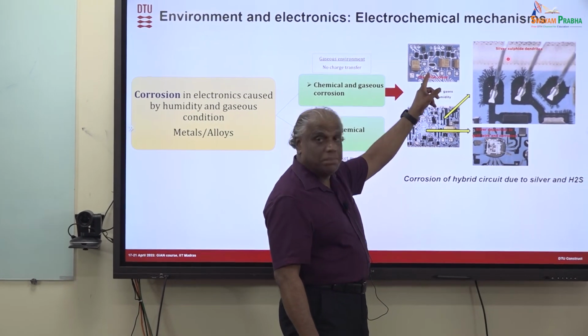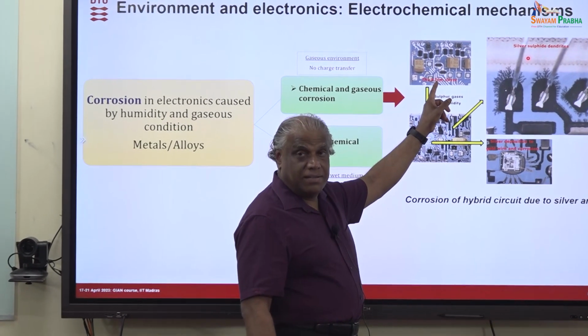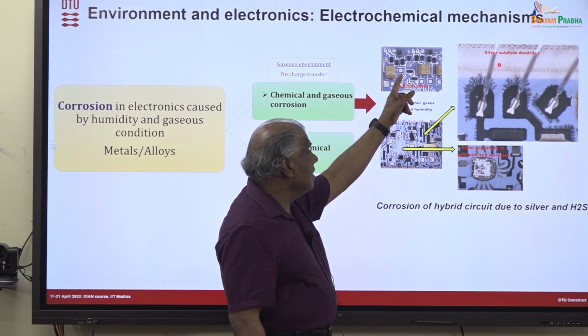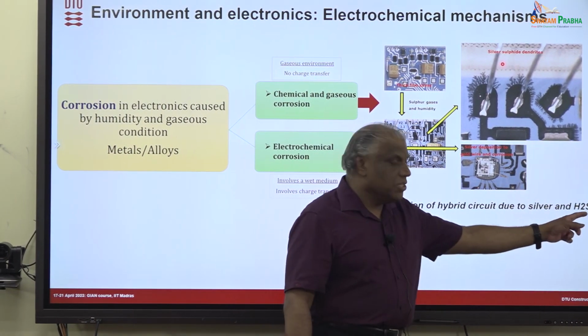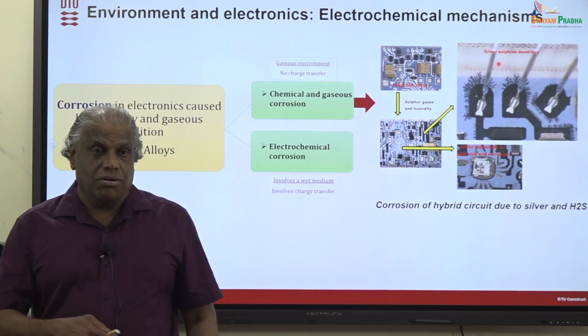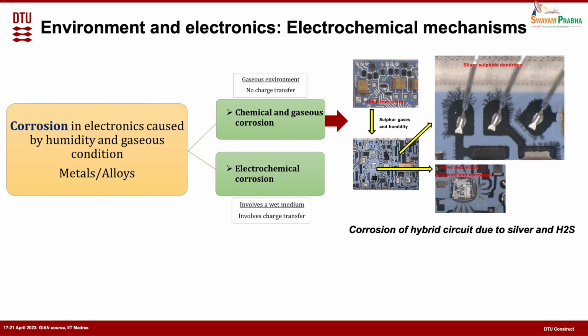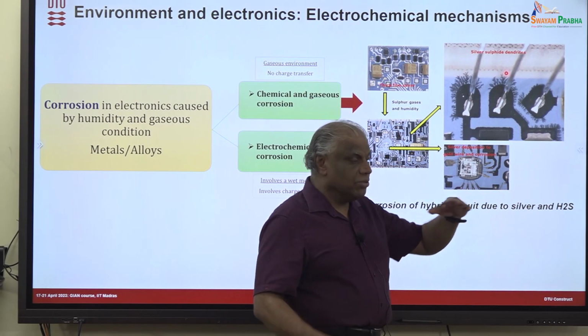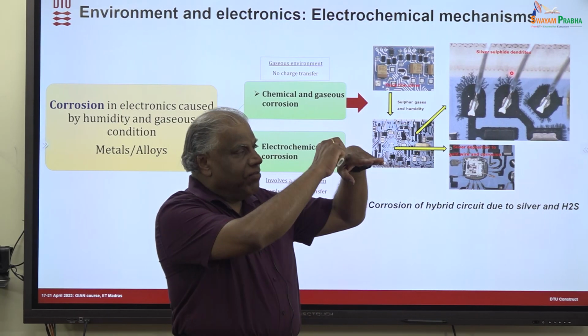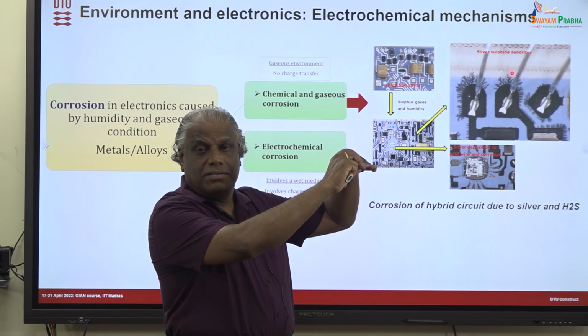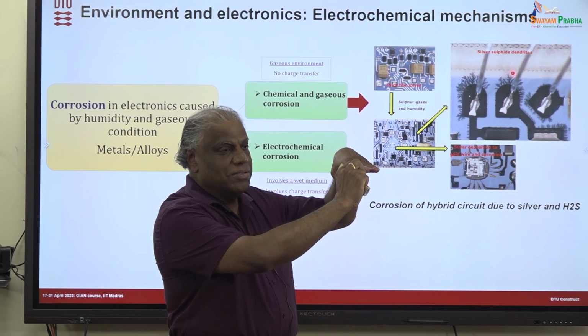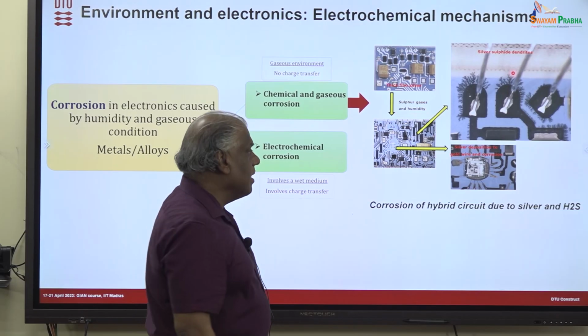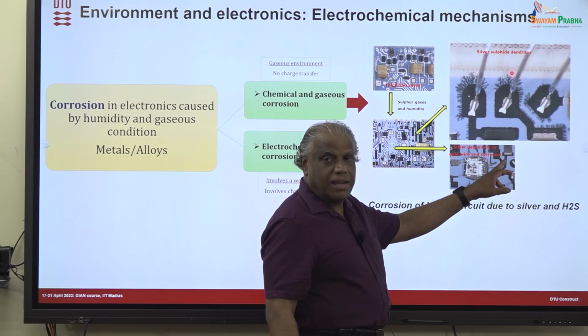All these conduction lines are printed on top, using a silver ink, and then they fire it. Since there is silver, and silver is very susceptible to H2S and SO2 gas, slowly in H2S conditions these silver lines will corrode. That's the black color which is forming: silver sulfide. All these dendrites that are forming are also silver sulfide. But what is the problem? When these lines are converted to black silver sulfide, you think you have a thickness of this much of silver, but now from the top, part of it is converted to silver sulfide. Silver sulfide is not conducting. So the actual thickness of the silver line is reduced, and that silver line cannot take the electrical current, and then you have a problem here.